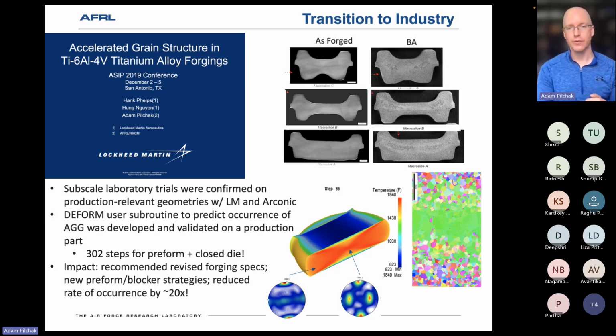We developed a user subroutine in DEFORM that took into consideration that critical strain. So you need to have a strain of about 1, but it also had a pretty cool way of aggregating the amount of strain that was put in with plane strain compression. So we had kind of 2 clocks running, and if both of those critical conditions were met, the subroutine calls out locations in the forging where the strain was high enough and it was close enough to plane strain compression that you may have a problem with abnormal grain growth. So that gives forging designers a tool to try to develop a preform shape and a forging strategy that avoids the abnormal grain growth.